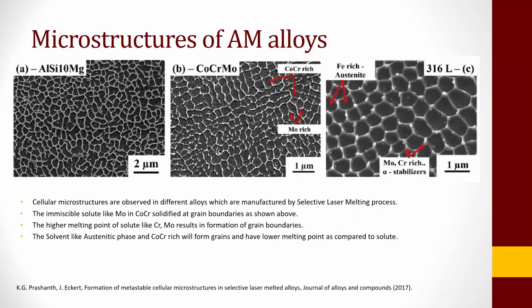And very quickly about the microstructures of additively manufactured alloys. So I have chosen 3 different examples here. The first one is aluminum, silicon, magnesium, the second one is cobalt, chrome, molybdenum, and the third one is 316L stainless steel. So you could see that, for example, when you focus on cobalt, chrome, molybdenum, the higher melting point of solutes like chromium or molybdenum results in the formation of grain boundaries. And the immiscible solutes like molybdenum in cobalt chrome are solidified at grain boundaries, mainly at grain boundaries. And so on and so forth.